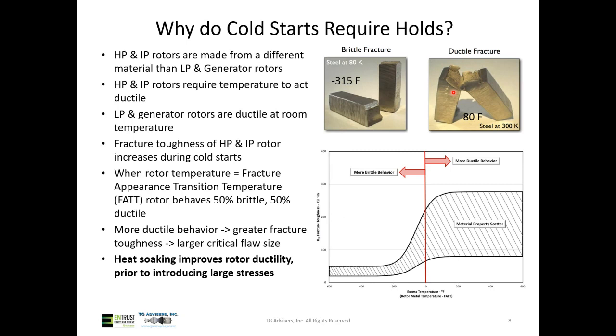So if your startup is calling for these holds and you're not adhering to them, there's more risk for a rotor burst event, which obviously is not something that happens very frequently, but it's a very significant event. So it's something that we're obviously very careful to avoid. So that's one comment,